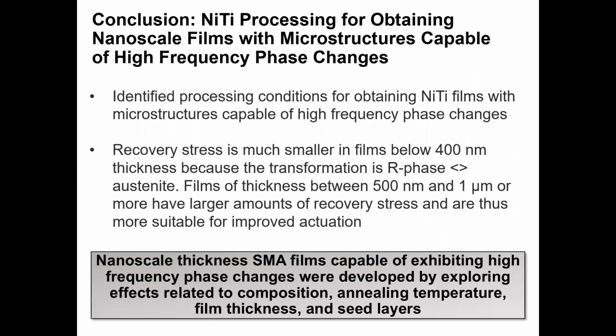So in this section, I identified the necessary processing conditions for obtaining NiTi films with microstructures capable of high frequency phase change. What I found is that recovery stress is much smaller in films below 400 nanometers thickness because the transformation is predominantly between R phase and austenite. Films of thickness between 500 nanometers and 1 micron or more generally had larger amounts of recovery stress and were thus more suitable for improved actuator performance.